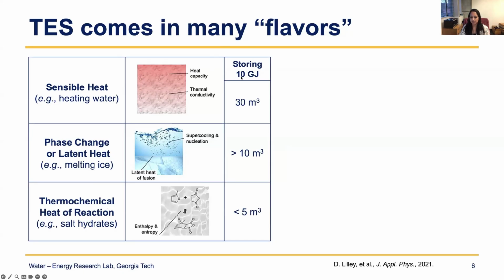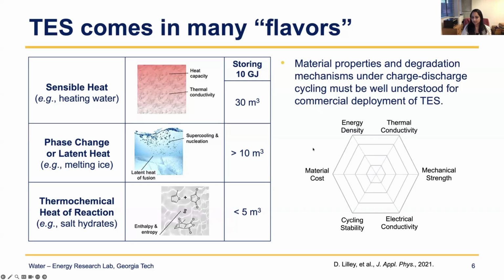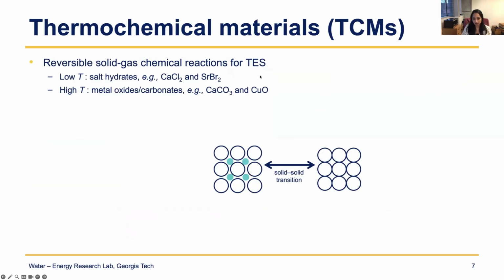And if we compare how much energy you can store, so if I want to store 10 gigajoules of energy in any of these three types, you can see the volume of material needed is very different. These thermochemical materials are the most energy dense, so you can get very compact energy storage solutions by using chemical reactions for heat storage and release. For all of these cases, we need the energy density to be high. We also need high thermal conductivity and high electrical conductivity, so we can charge it with electricity. And most importantly, we need cycling stability. As we charge and discharge over hundreds and thousands of cycles, how does the performance change? That's what we study specifically with these thermochemical materials, or TCMs.